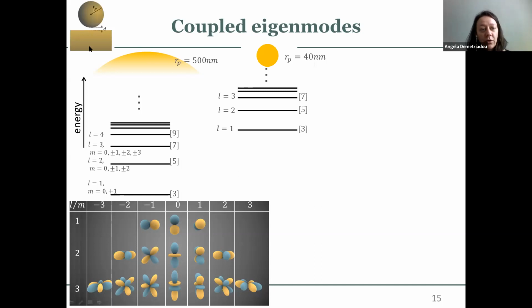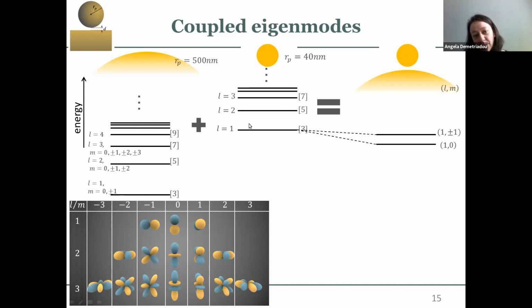Now, if I want to look at the nanoparticle-on-mirror, what I can do is couple this very small nanoparticle with this very large nanoparticle, and I have an approximate nanoparticle-on-mirror system. And the way that I structured the modes here for the 2 systems is I put them where they should be energetically, so on this axis here. So my first order mode for the very small nanoparticle is aligned with the higher order modes of the very large nanoparticle. So when I bring the 2 together, what you start seeing is mainly enhancement of the modes of the very small nanoparticle, but you start losing the degeneracies of your modes. And the reason for that is you're breaking the symmetry of the system. So you do not have just a simple spherical nanoparticle. By bringing this one next to it, you're breaking the symmetry that you had before in the nanoparticle.